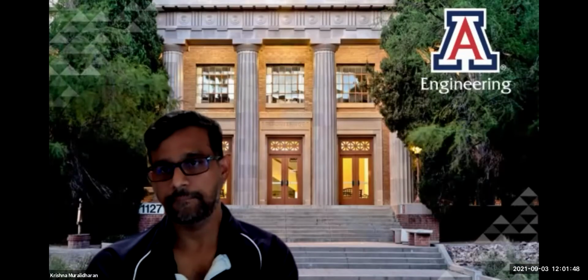Yeah, so it's interesting because we do know from lots of studies looking at these apatites geologically, because carbonated apatites do exist geologically, and we see a lot of research on these crystals in Earth and planetary sciences or geology departments, that removal of the calcium creates vacancies, and those vacancies could then possibly have a mechanical effect. Now, we know from the study that we did with the mechanics of the crystals that when we were adding or removing carbonate from the crystals initially, we were creating more vacancies. But the loss of calcium and carbonate seem to be very correlated. So usually what happens is you increase calcium, you decrease carbonate, and vice versa. But in this acidosis system, suddenly both of them are being removed. And that hasn't been understood from a charge balance perspective.